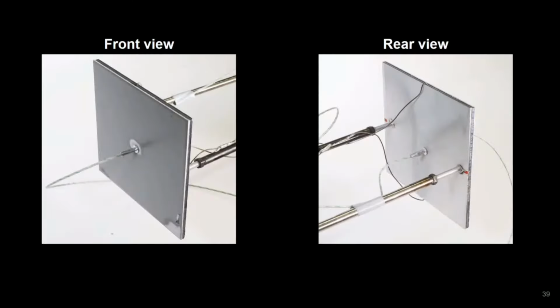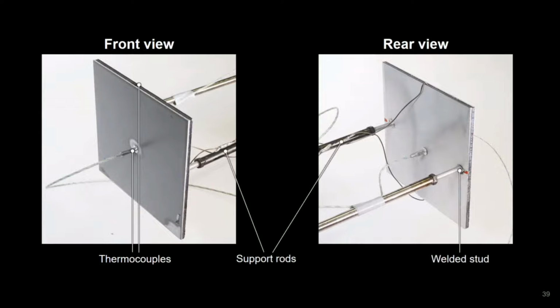The front view in this slide on the left shows the heated face of the sample. So the face on the left in that leftmost photo is showing you the face that was heated during the experiment. This photo also shows that we installed thermocouples on and within the samples to measure the temperatures of the aluminium facers and the polyethylene core material, and that studs were welded to the sample's aluminium skins, as shown here in the right-hand image.